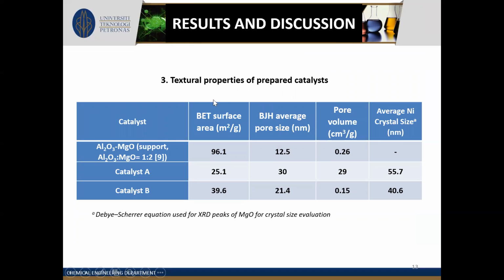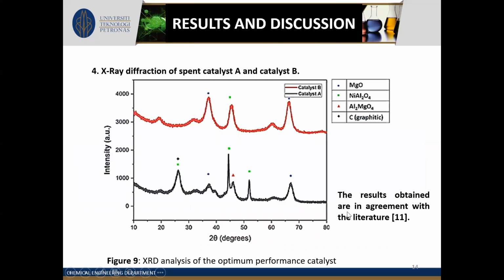We also did the surface area analysis. We can see that for the support, the surface area is 96.1 square meters per gram, which decreased to 39.6 after the impregnation of the catalyst, which is still higher than the single-step synthesized catalyst, that is 25.1 square meters per gram. We can also see that the average crystal size for catalyst A is bigger, 55.7 nanometers, and for catalyst B it is 40.6, which has been determined by the Debye-Scherrer equation from the XRD data.